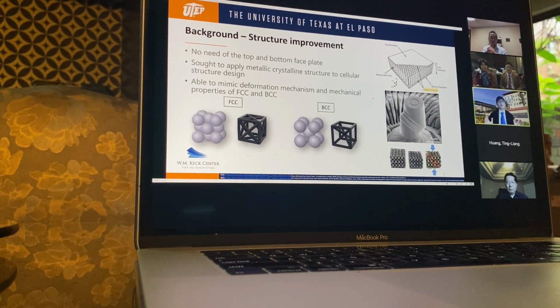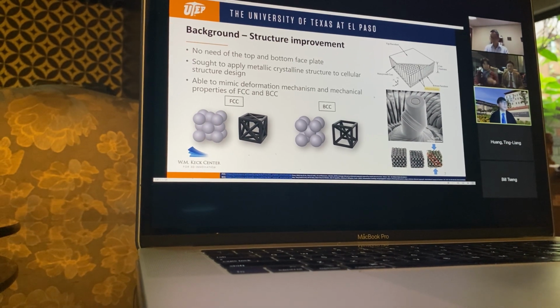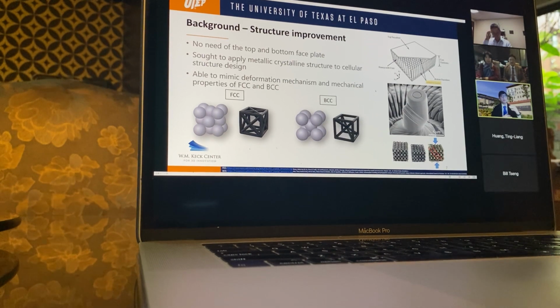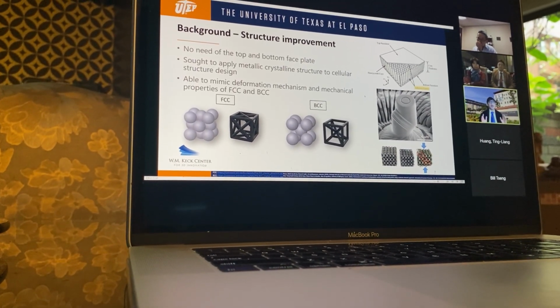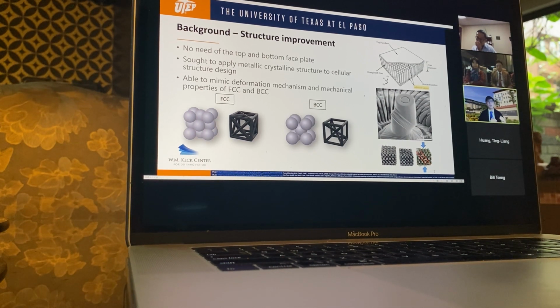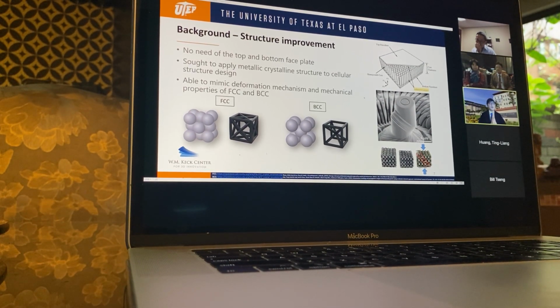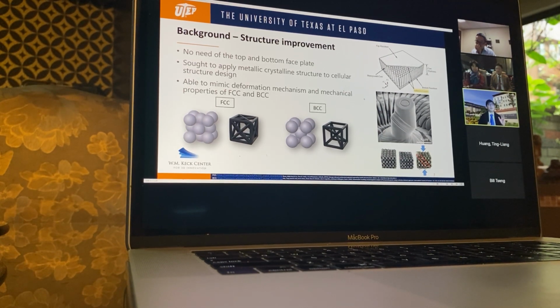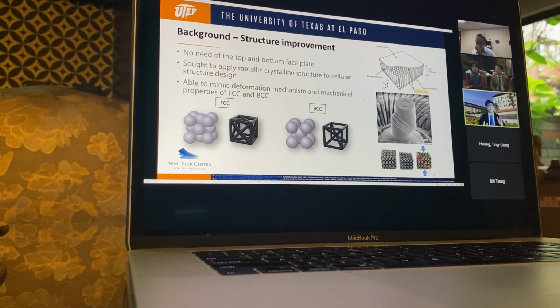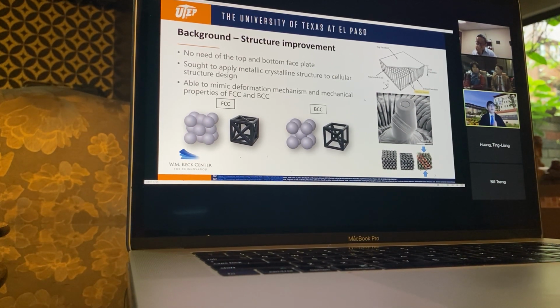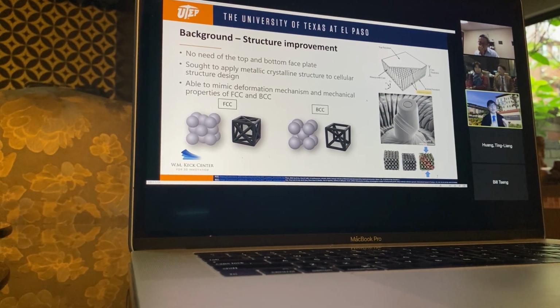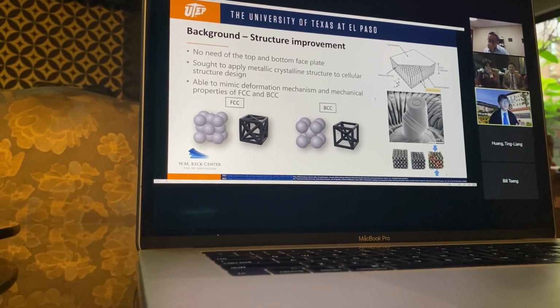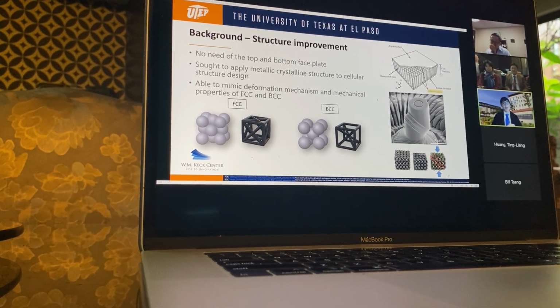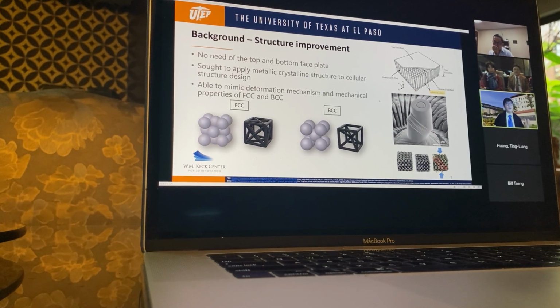Okay, so we improved the sandwich structure design on the core section and abandoned the outer part of the sandwich structure, which means we didn't add the top and bottom sheets to our structure design, and the whole structure became like a cellular metamaterial structure. In the beginning of the CAD design, we were inspired by metal crystal structures such as FCC and BCC. There are 5 elements in each face of the FCC. One of them is located at the center of the face. That's why it's called face centered cubic.